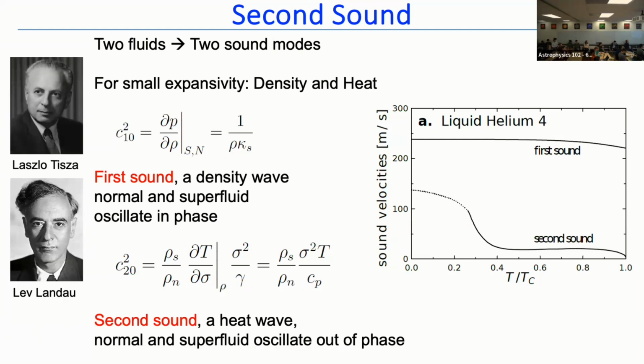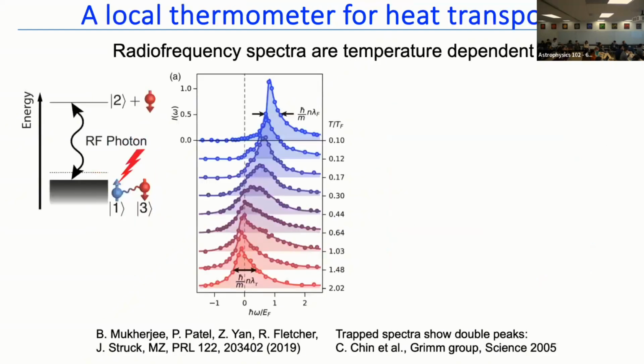And indeed, that's the case. And the interpretation is one sound mode is just the standard sound where superfluid and normal fluid go together. And the other sound mode is an entropy wave, almost purely an entropy wave, where normal and superfluid oscillate out of phase. And the density pretty much doesn't change. So that gives rise to two sound modes, first sound and second sound. Second sound dies off at Tc. It's kind of low and rises at very low temperature. So we felt like that would be nice to see. It would be cool if you could see that second sound directly, but we wanted to see it in the heat. But how do you measure heat was the question.